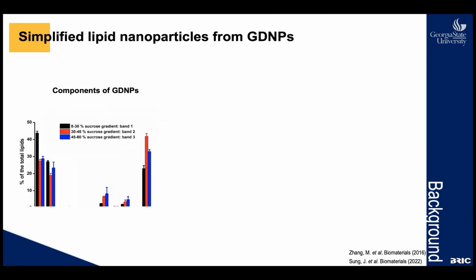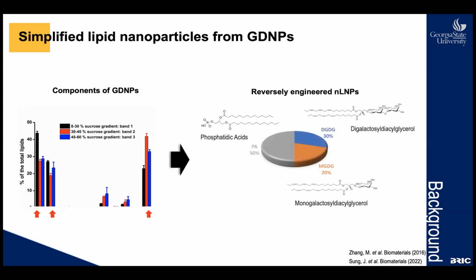Based on the GDNPs, we discovered that 3 major lipid components comprise more than 90% of the original GDNPs. I apologize for this uncropped data I'm showing right now, but this is lipidomics data that shows that the 3 lipids, including DGDG, MGDG, and PA, comprise more than 90% of the GDNPs. So we hypothesized that mixing these 3 major lipids at the ratio found in the subgroup of GDNPs would enable us to form a new nanoparticle that would retain the nanostructure of the GDNPs and may be used as a well-defined gene delivery system.